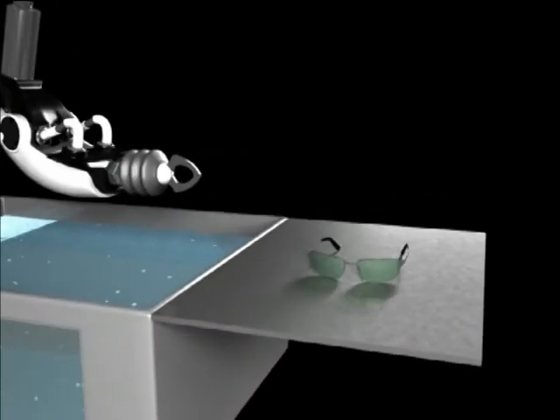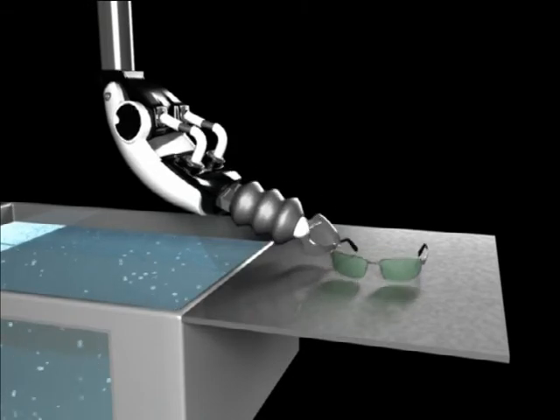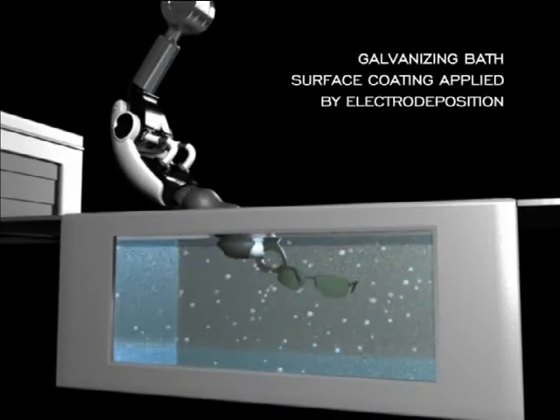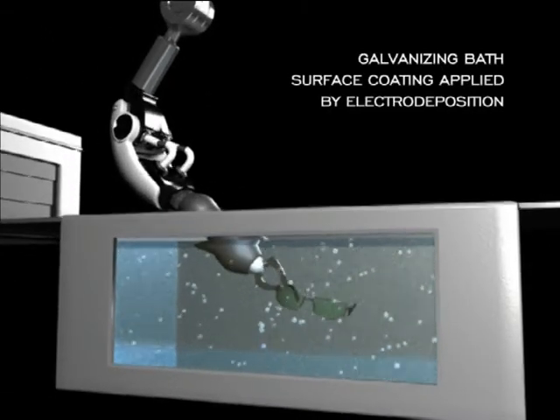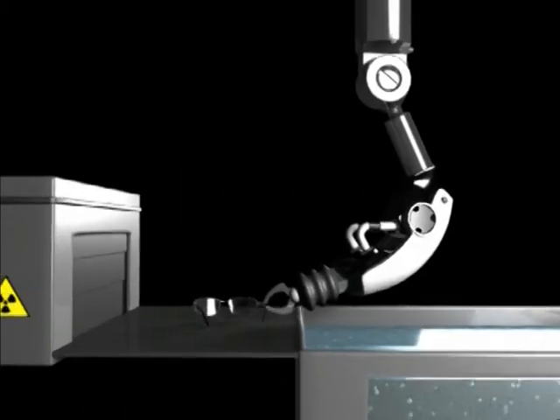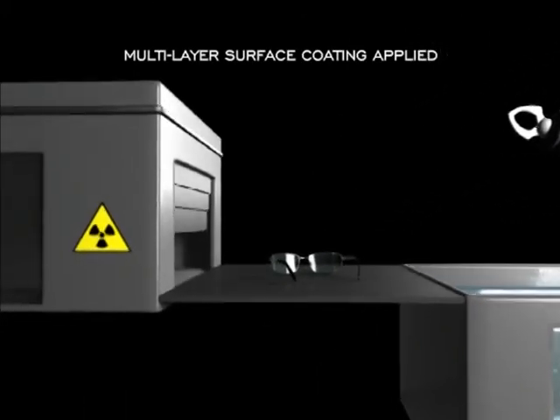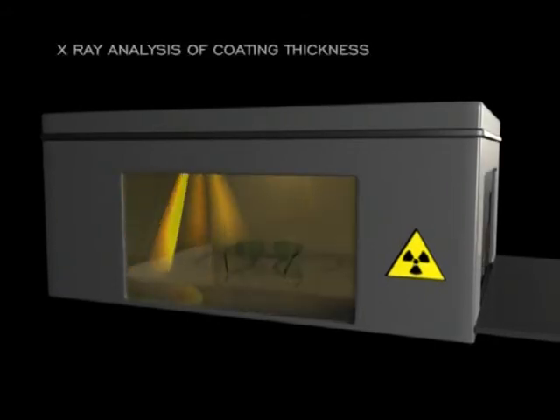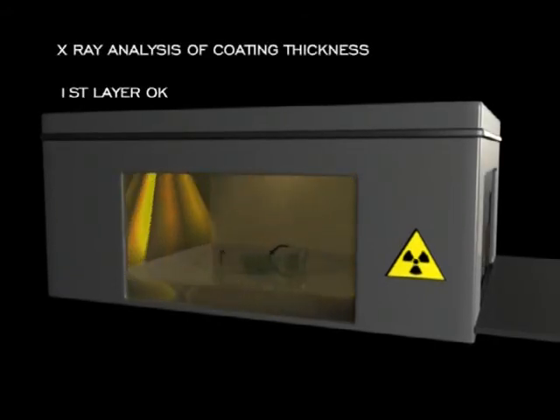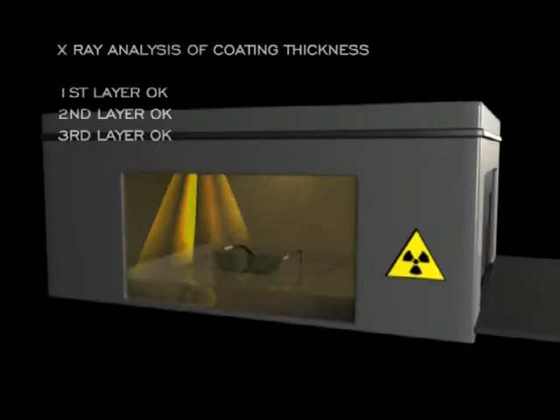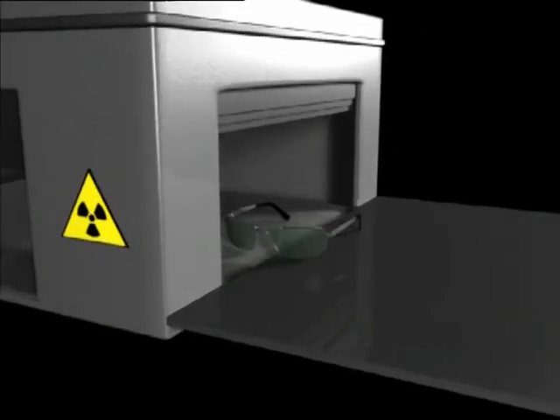Surface coating test. Surface coatings strengthen frames and protect them from corrosion by external agents. This sort of protection is achieved through galvanic baths, electroplating. The surface coating test uses X-ray instruments to check the exact thickness of the different layers. Furthermore, by submitting the frames to a tearing strength test, the coating's adherence is also controlled.